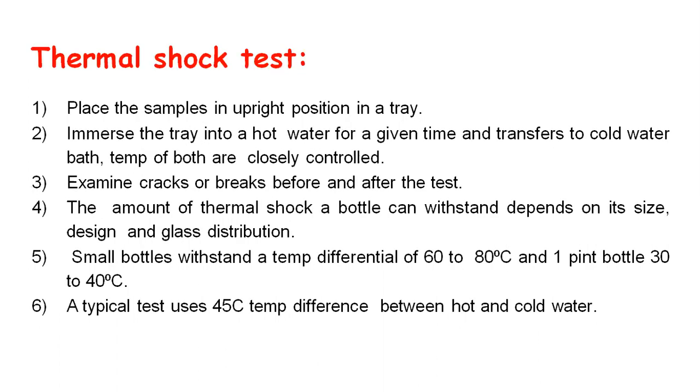Thermal shock test. Place the samples in an upright position in a tray. Immerse the tray into hot water for a given time and transfer to a cold water bath. Temperature of both is closely controlled. Examine cracks or breaks before and after the test. The amount of thermal shock a bottle can withstand depends on its size, design, and glass distribution.